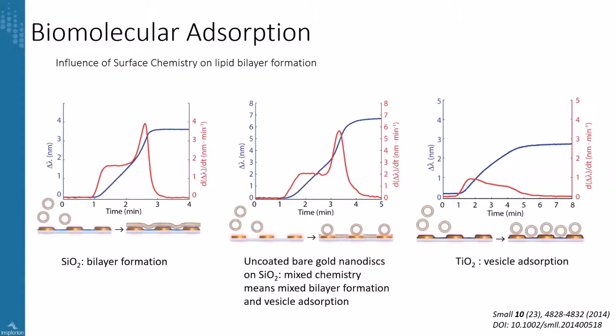And you can see in the silica coated sensors, there's a lipid bilayer formation with a standard curve that we were just looking at. But for example, in titania coated sensors, there is only adsorption and not the formation of the lipid bilayer. So the surface influences how the vesicles will distribute or not. In this study, uncoated sensors were also tested, and these uncoated sensors have silica in between the gold structures. And what was observed was this hybrid between lipid bilayer formation, which occurred on the silica part of the sensor, and vesicle adsorption, which occurred on the gold structures.